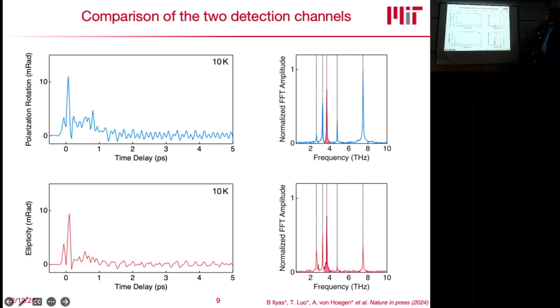And so all of these dashed lines here show you the position where Raman measurements found modes in the system, and we actually find perfect agreement between these measurements. And also what we find here, this red mode is actually our magnon. So we can see coherent oscillations of this magnon mode, which shows us that we are sensitive to magnetization dynamics, because once your magnon is oscillating, it transiently creates and destroys a magnetization in the material. And as we see that these two measurements, polarization rotation and ellipticity, are very similar, from now on I want to focus on the polarization rotation, because the signal to noise is slightly better.